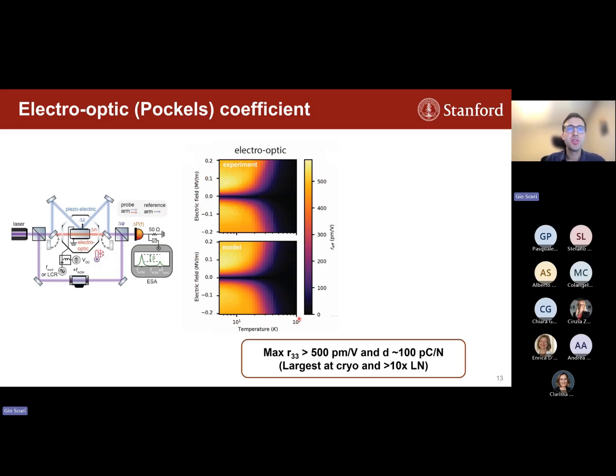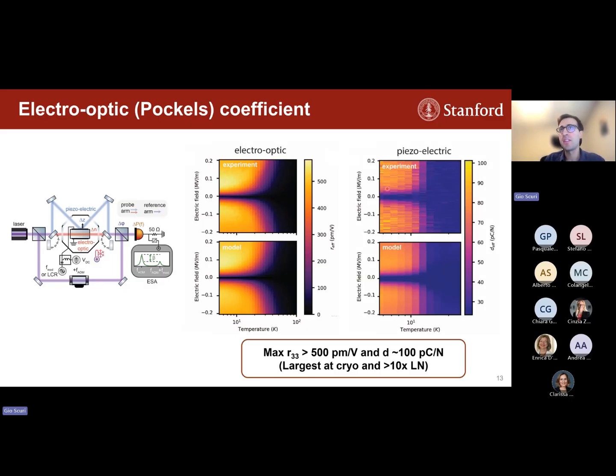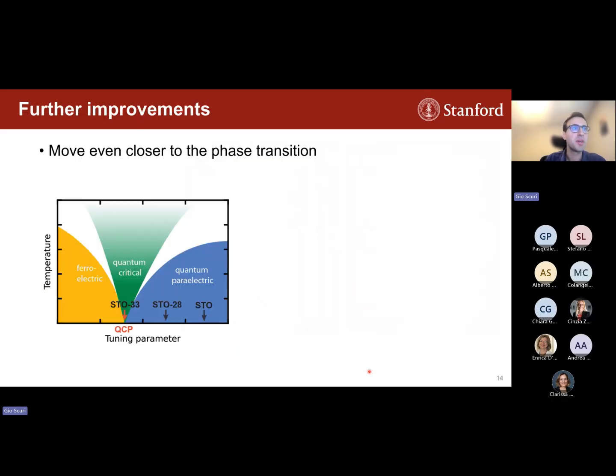And what you see is that as you cool from room temperature down to cryogenic temperatures used in quantum experiments, you get a very strong enhancement in the Pockels coefficient, and you also get an enhancement in the piezoelectric coefficient. Respectively, there are around 500 picometers per volt and 100 picocoulombs per newton, which are the largest reported at cryo, and more than 10x lithium niobate.